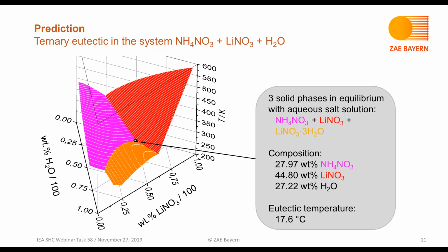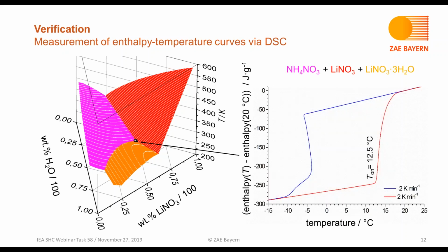In the calculation step, the information that we get is the three phases that are in equilibrium with the salt solution, the eutectic composition, and the eutectic temperature, as indicated here. And now we are performing calorimetric DSC measurements with a sample of that composition. In this case, it's an example of a successful verification, because what we observe is a single and quite narrow melting transition. This is shown by the red curve. The blue one is upon cooling, the red one is upon heating. So this eutectic is experimentally verified.